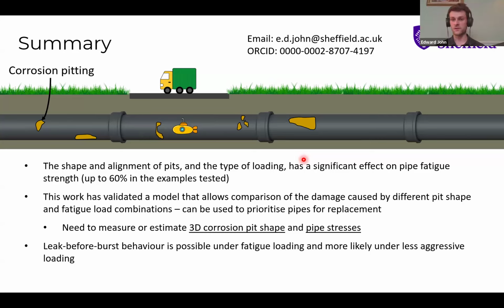Stresses from pressure are relatively easy to understand. We measure the pressure in the pipe and we can predict those, but there's a whole host of external loads that pipes can experience, and our ability to predict those is quite poor generally. So really this is a call to try and understand the factors surrounding a pipe to be able to better manage them. In the shorter term, though, some of the stuff around how the leaks behave shows some interesting things that we can consider. So, you should look for your leaks when your pressures are highest, because they're less likely to be shut, for example.